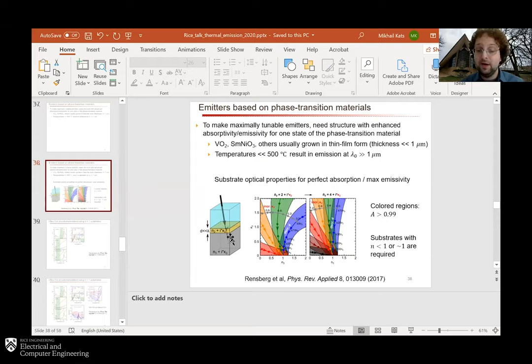What we found is that you can very often have situations, if you have a thin film that's much thinner than the wavelength on the right type of substrate, you can have potentially a very high degree of optical absorption, even though the film is much thinner than the optical wavelength, as long as you have high loss in the thin film. In the case of these thermal emitters, the samarium nickel oxide film is about 150 to 200 nanometers, and the wavelengths at which we're looking are about 8 to 14 microns. And yet you still have this high emissivity at one temperature and a lower emissivity at another temperature, and the effect works. But because the films are so thin compared to the wavelength, the angle-dependent effect is very small. You only really start seeing it at about 40 or 50 degrees off of normal, for both P and S polarizations.